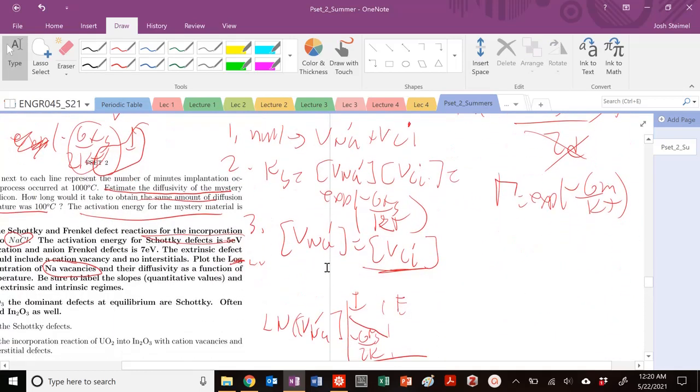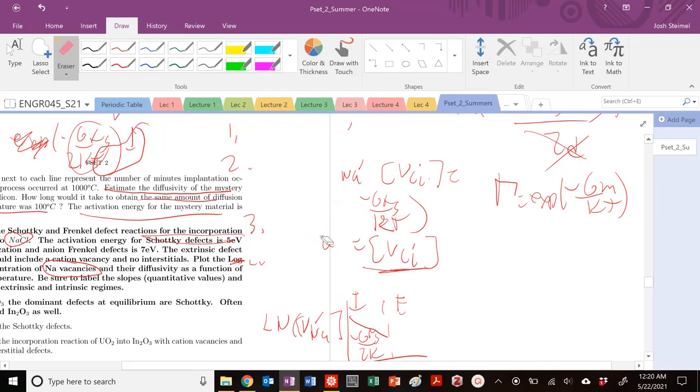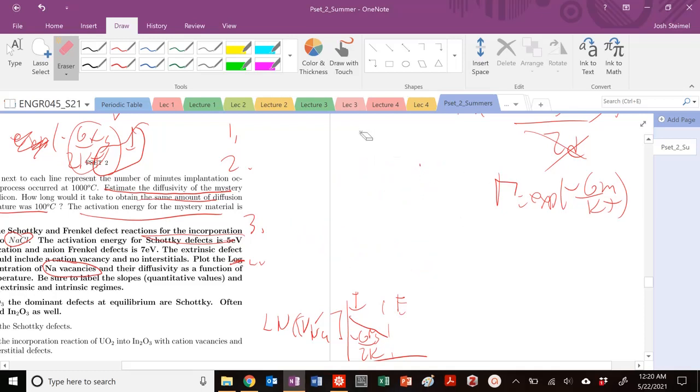So again, we're still interested in these different types of steps. I'm just going to pause this here. So it's CdCl2 into NaCl. I need to make sure that one of my defects is a vacancy in Na because that's what we're interested in. And I'm also going to do a Cd replacing Na, so that's a charge of +1, and then I'm just going to have a 2 Cl_Cl^x, and then a 2 here. Done.